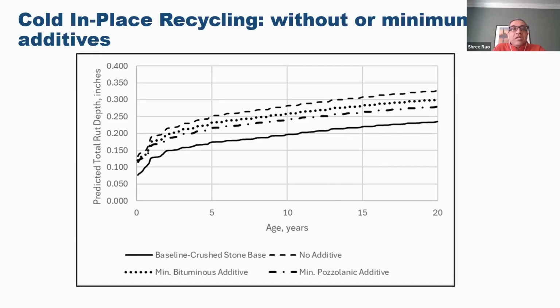And if there's no additive, then the rutting goes up from, let's say, about 0.23 or so to about 0.33 or so. So a little bit more rutting after 20 years with the cold in place recycling, as opposed to essentially a new asphalt pavement for the same thickness.